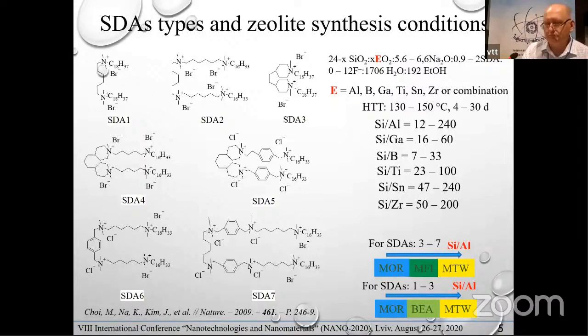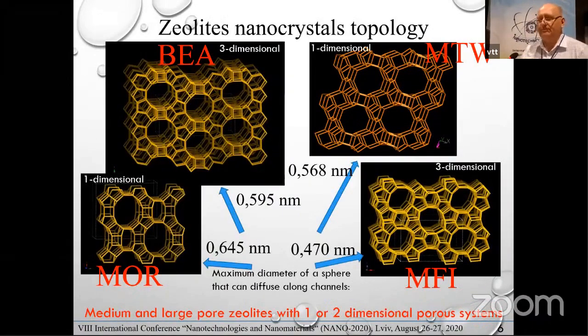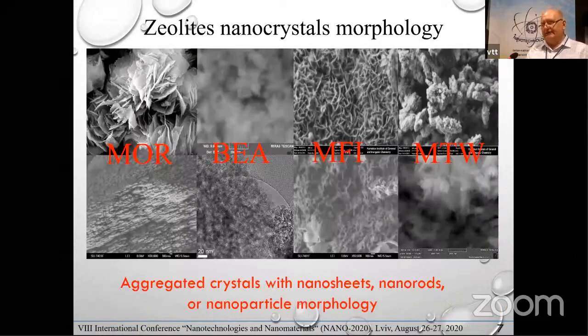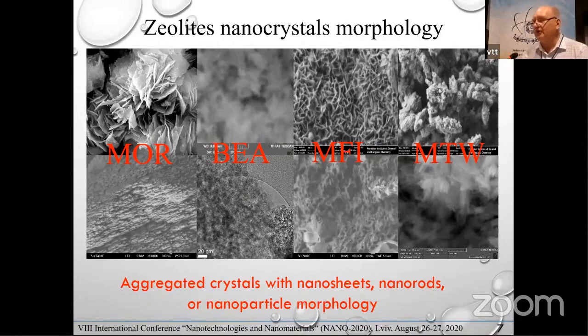The structures of these zeolites are presented in this slide. These zeolite structures are slightly different, especially in the size and dimensionality of micropores. The morphology of such materials is different and can be nanosheets, nanorods, or nanoparticles, which intergrow into different agglomerated hierarchical zeolites with a large volume of mesopores, which can be used as transport mesoporous channels. And of course, with some domination of some surface of zeolites as the dominant surface.